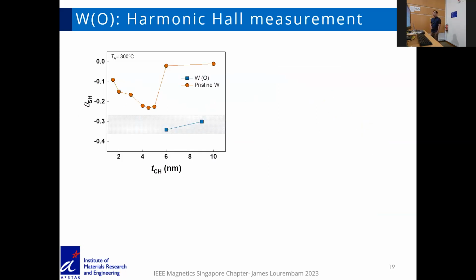Then we come to the spin Hall measurement of this oxygen-doped tungsten system. As I mentioned, at low thicknesses the tungsten is in the beta phase and at high thickness it is in alpha phase. This is easily observed from the spin Hall measurement. The red dots here are just pristine tungsten, and we can see that the value drops suddenly after it transitions to alpha phase. When we use the multilayer, we find that the value stays high, even up to 9 nanometers. The other thing is that on our 200 millimeter deposition platform, we're not able to reach 0.3, which is quoted in the literature. Of course, these are all after annealing at 300 degrees Celsius.